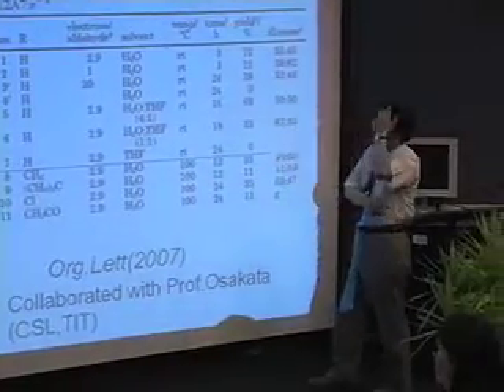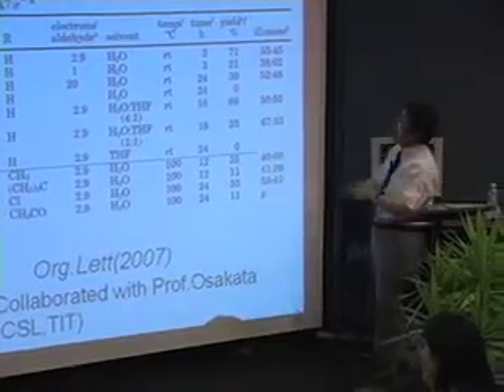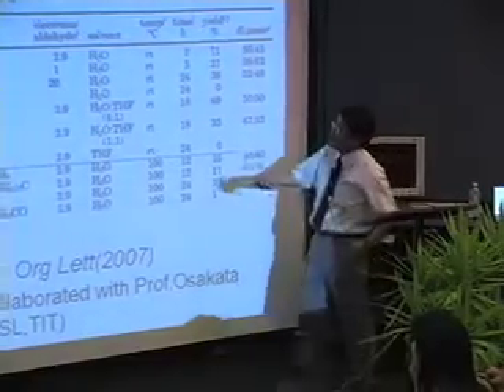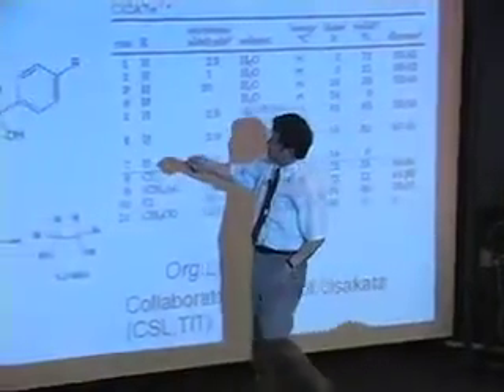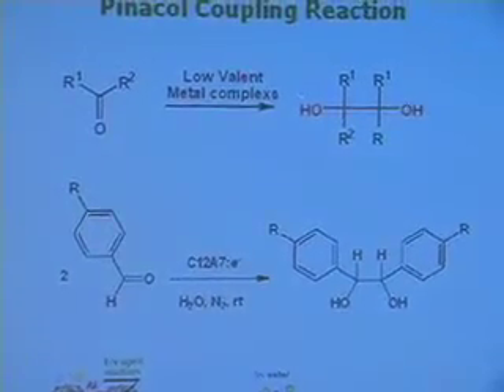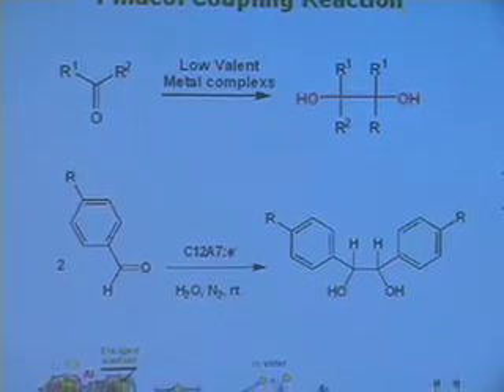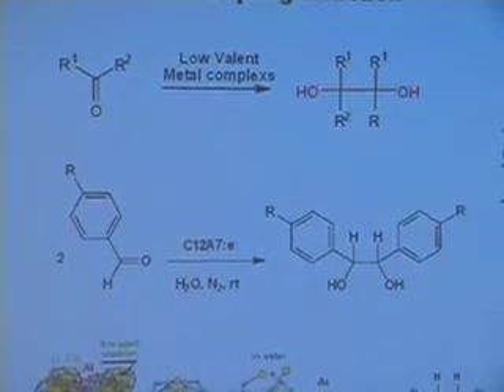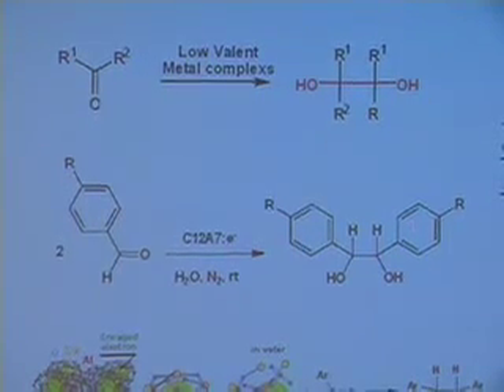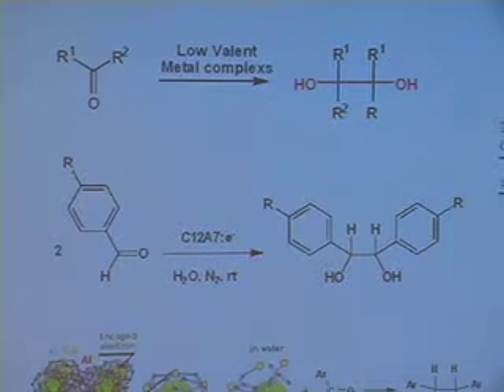So that doesn't work chemically as a reducing reagent. So we applied C12A7:e in the chemical reaction, a C-C bond formation, like this: aldehyde coupled, this is ketone, and they couple to each other to form a C-C bond, with two OH groups. So we examined this reaction.